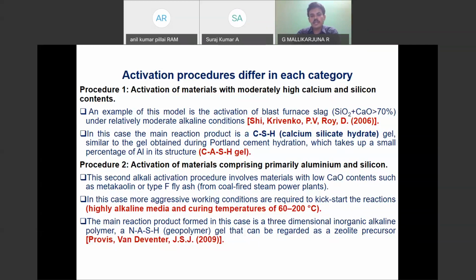And if you go with the very low, that is, low calcium materials for the activation process, such as metakaolin or the class F type of fly ashes, you have to go with a high alkaline media, and the curing temperature you have to maintain from 60 to 200 degrees centigrade. And there is a formation of the inorganic alkaline sodium aluminum silicate hydrate gel. And here